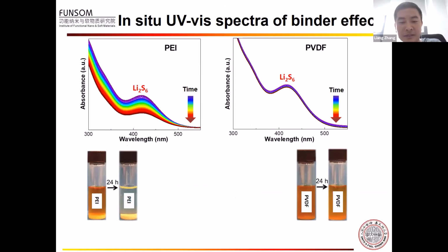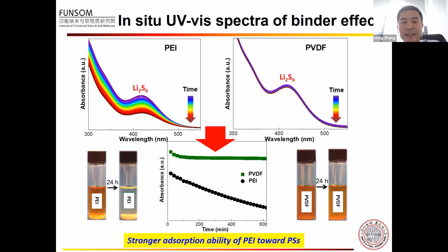To demonstrate the strong interaction between polysulfide and the PEI binder, we first perform the in-situ UV-Vis experiment. The left is the PEI result, the right is the PVDF result. We can clearly see the feature of the lithium polysulfide continuously decreases in 10 hours, while for the PVDF, the intensity doesn't change. In addition, for the PEI binder, the typical yellow-gold color of the polysulfide becomes almost transparent after 24 hours. So this result clearly indicates the PEI binder has a very strong adsorption ability towards polysulfide.